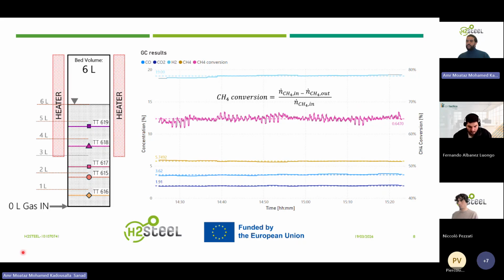From the gas composition at the outlet that is obtained from the micro GC, we can then calculate what's called the methane conversion, using this equation, which is basically evaluating the percentage of consumed methane with respect to the one at the inlet.